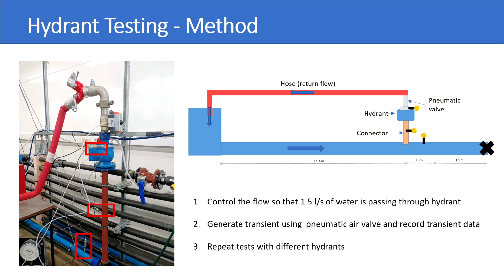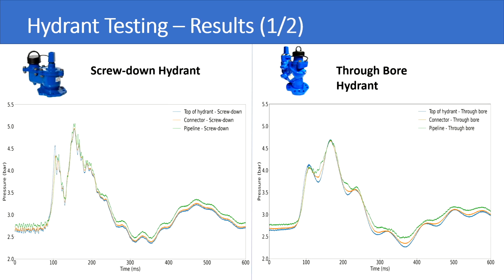And then we have measured the pressure response at the points which you can see in the red squares. And then we've repeated that with different hydrants. So what do we see? With screw-down hydrants and through-bore hydrants, we get a very different pressure response.